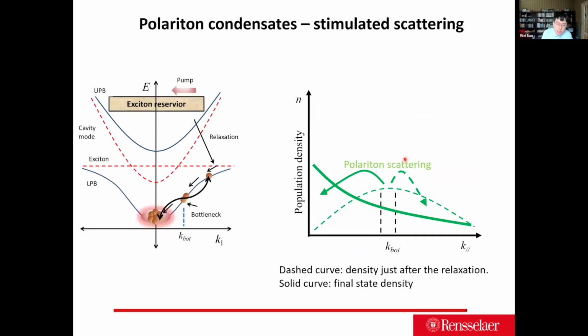The other interesting thing with the system is that now we have the upper polariton and the lower polariton state instead of the traditional exciton and the strongly coupled cavity photon. Once you pump the system, you generate a lot of exciton reservoir, and then the exciton reservoir relaxes and forms a bottleneck region, and eventually runs into the condensate.